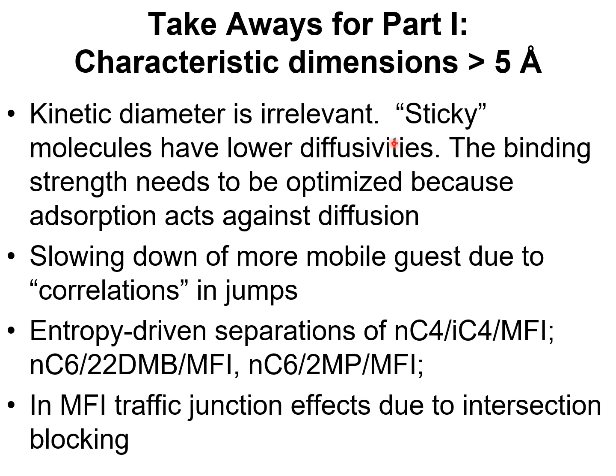Small differences between the window aperture lead to differences in diffusivities by about 2 orders of magnitude, and this can be exploited to obtain high permeation selectivities.